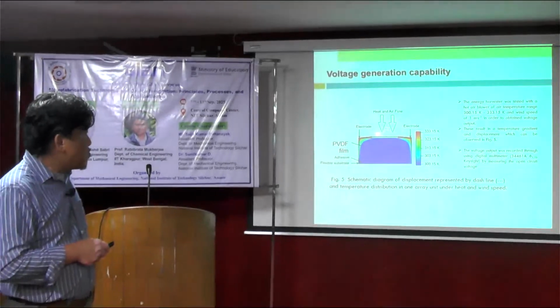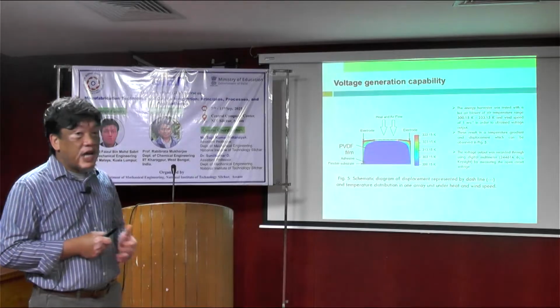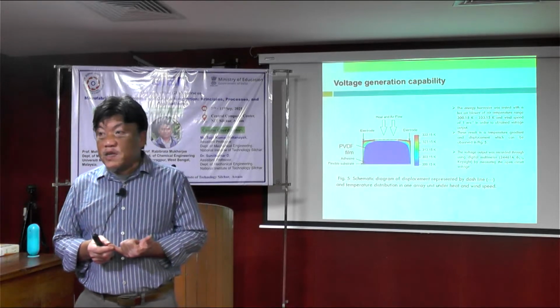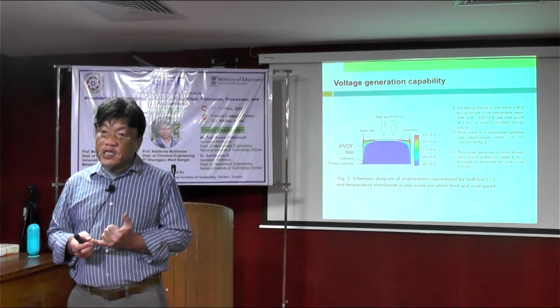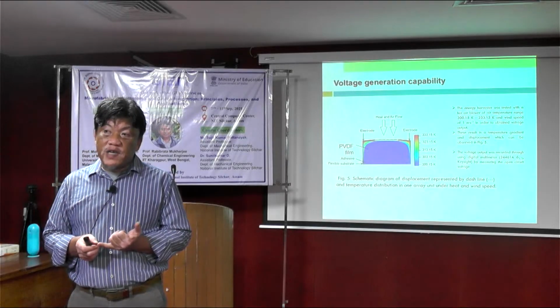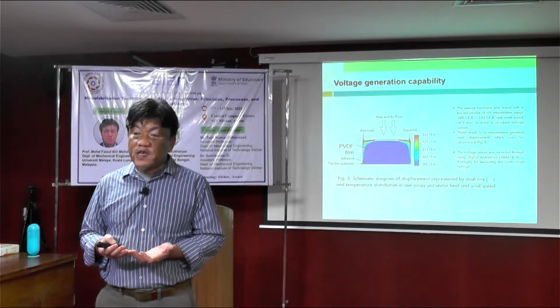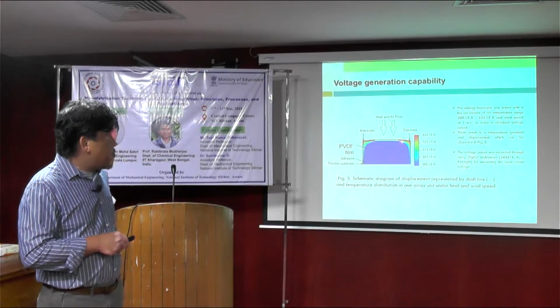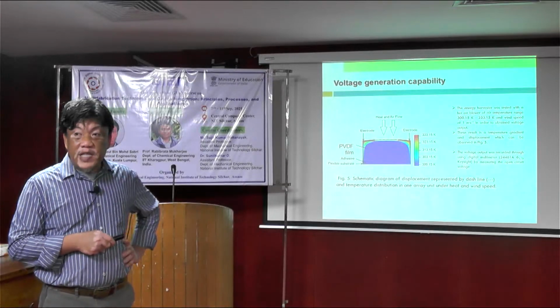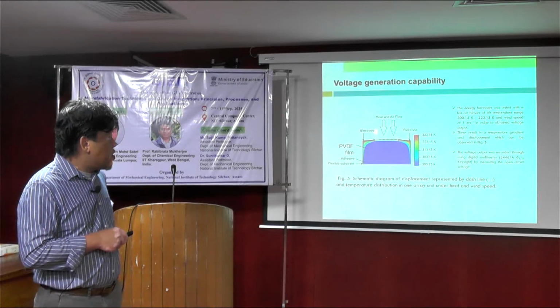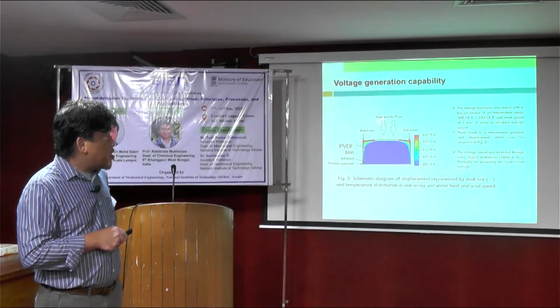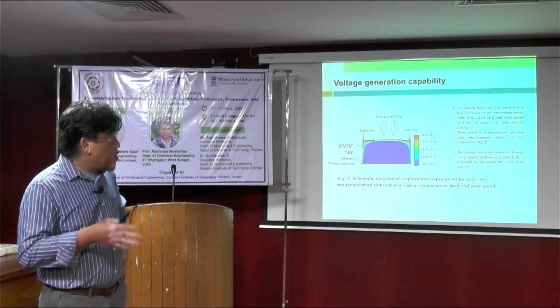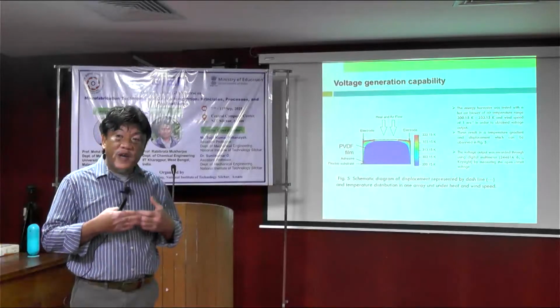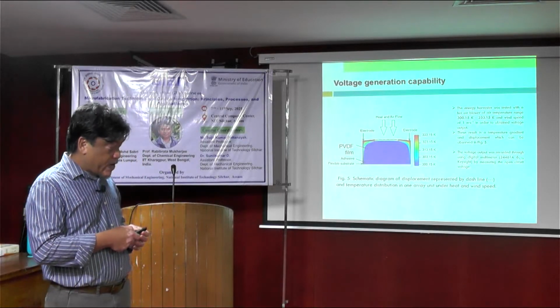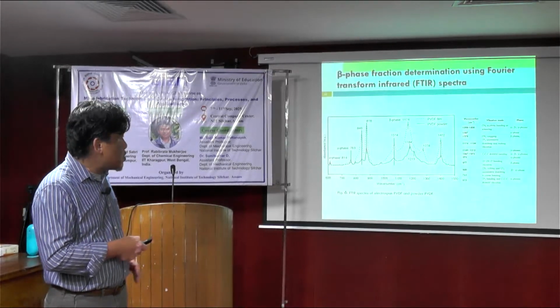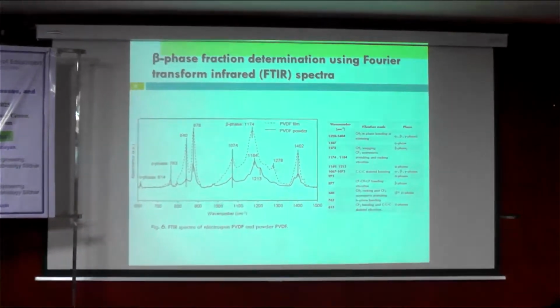Then you do the testing, because this is a hybrid system, which is piezoelectric and pyroelectric. Piezoelectric, as I mentioned, you can harvest electricity by providing strain to the system, while pyroelectric is about heat. You have a thermal fluctuation, then you can get electricity. So because of the nature of PVDF at beta phase, you can have both piezoelectric and pyroelectric. So if you blow hot air to the system, you can harvest the heat from the hot air, and also for the blowing of air, I mean the flow of the air, that can provide strain to the material itself. So that will provide a piezoelectric output. So beta phase of the materials here.